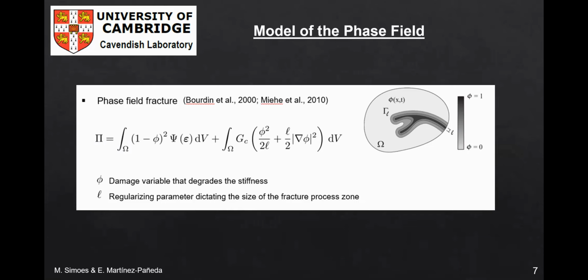Two things that I want to emphasize here. First, following standard continuum damage mechanics arguments, the phase field can be thought of as a damage variable that goes from 0 in intact material to 1 for fully cracked material points. And as a consequence, by increasing its value, it reduces the stiffness of the solid, as you can see in the first integral. Secondly, there is a gradient term and consequently a length scale. The model is non-local, which ensures mesh independence. Results are mesh independent as long as the length scale is resolved.